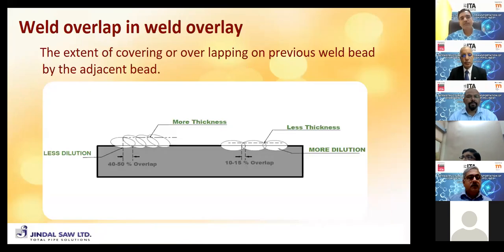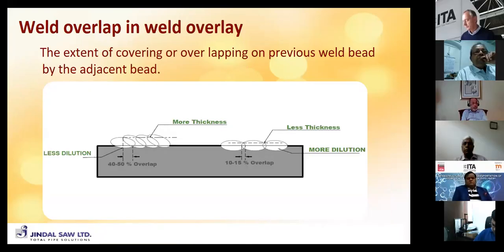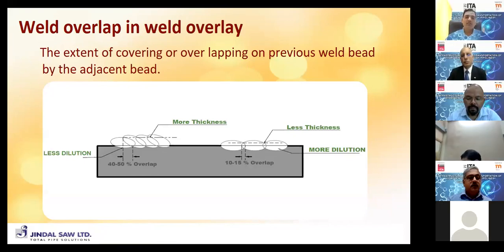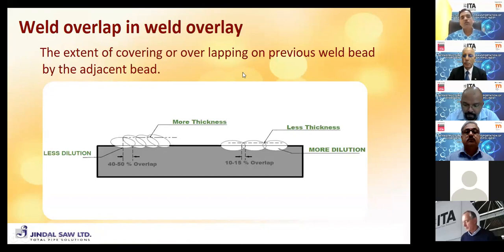Next, please. The problem with the weld overlay is that we have to deposit more to get the lowest dilution. If we deposit less, then dilution from the base metal will be more, so we will not get the accurate chemistry on the surface of the CRA. So this is a costly process, we can say, and has some other problems with it.